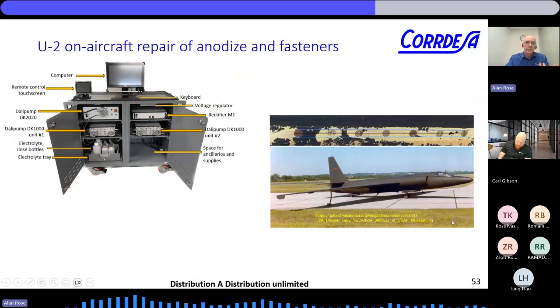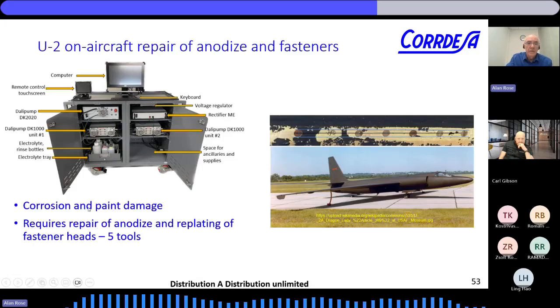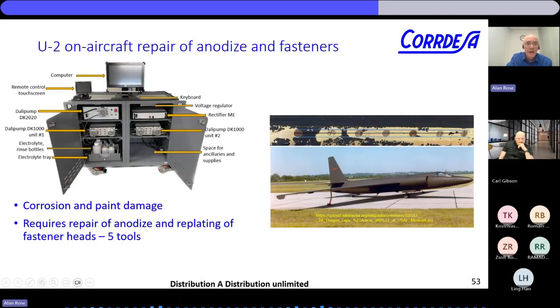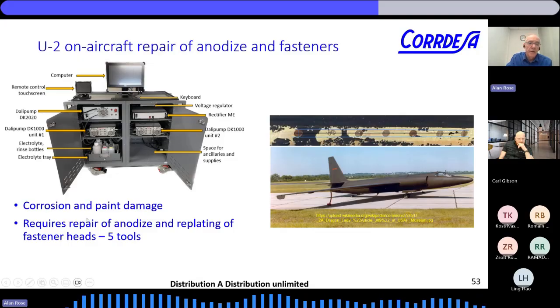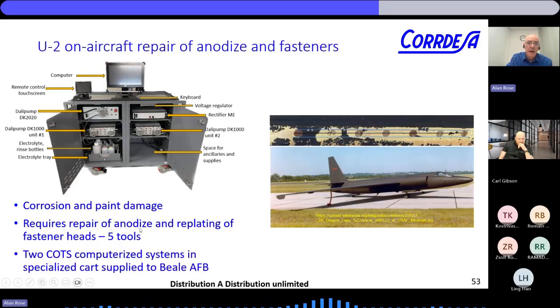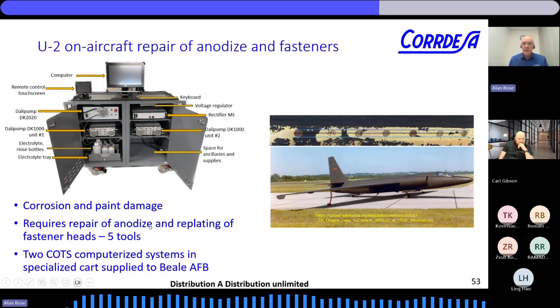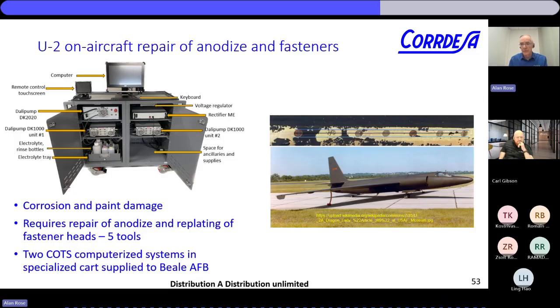Okay, so we took this further. What we did then was develop a system using the same non-drip approach, where there's actually corrosion. So this is a U2, just an old spy plane, a lot of corrosion on there. And we developed a way to remove that corrosion, replate the fasteners, and reanodize the damaged aluminum around the fasteners.